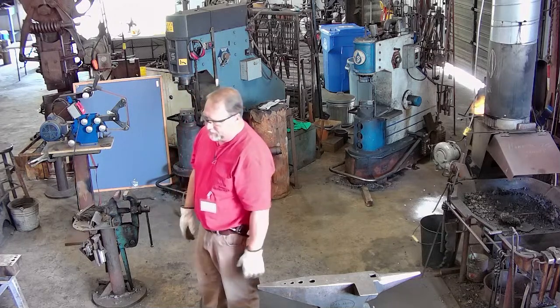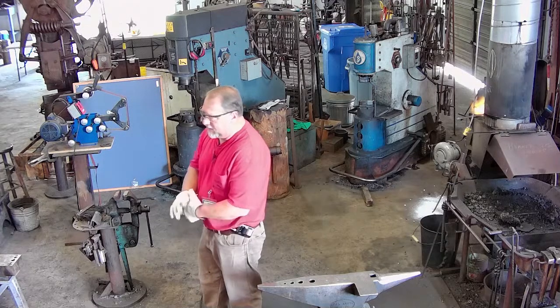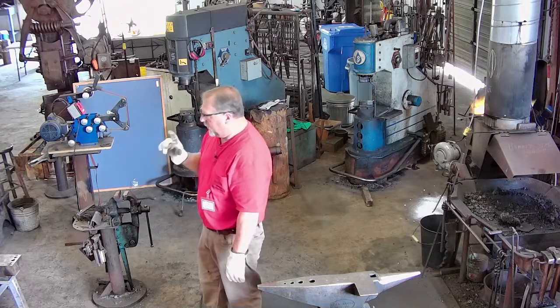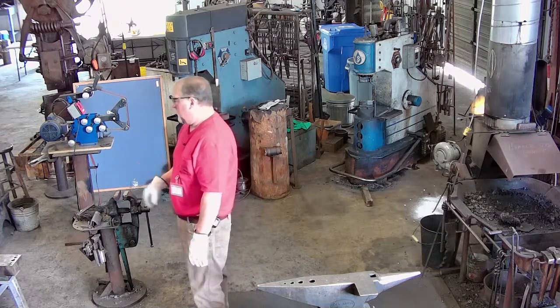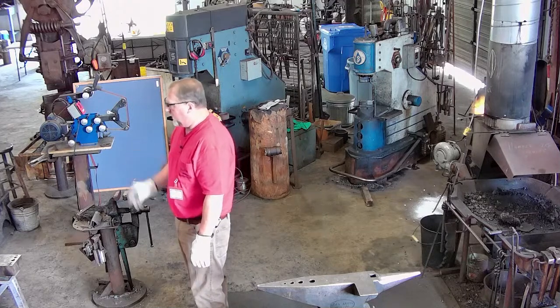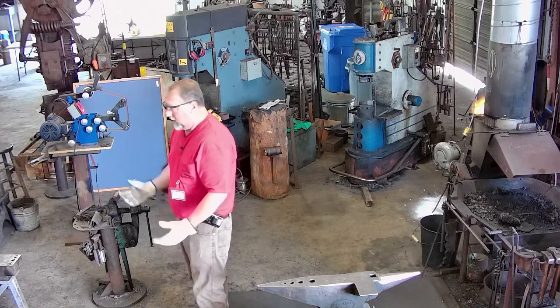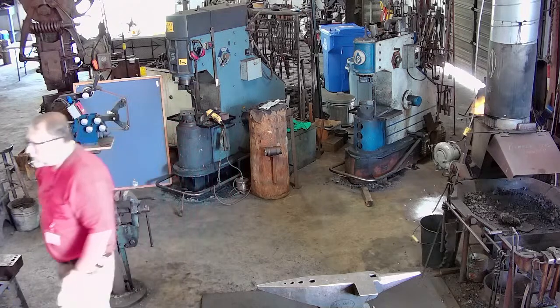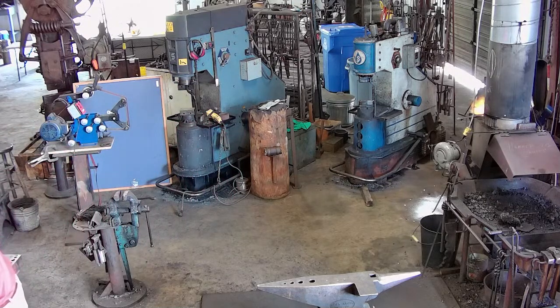I've heard the DeRosiers, when they did a demo down at Batson, their rule of thumb is you've got to reduce your stock by 50% before they're confident that you've got a good solid forge weld all the way through it. If you're using the press, when you turn it up on the side, the force that you're using, is it similar to like you said with the hammer, where you bite it up on it?